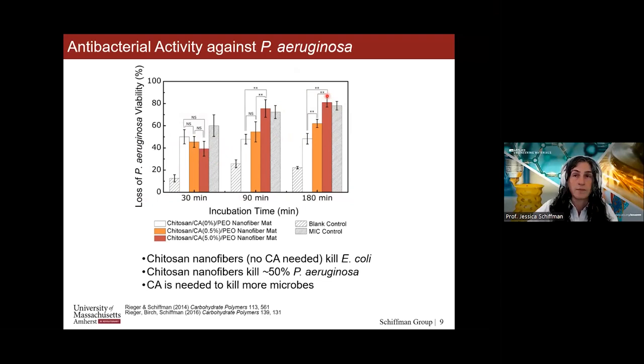And after 180 minutes, actually maybe even after 90 minutes, we have the same amount of killing as if we had this volatile essential oil just by itself in solution with the bacteria. So this is incredibly effective. I also want to note, I'm not even showing you the data for killing E. coli K12 because we didn't even need cinnamaldehyde. The chitosan itself killed all of these bacteria.